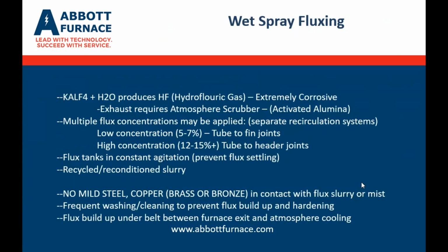As far as the HF gas, the hydrofluoric gas, it is extremely corrosive, which is why we're using an atmosphere scrubber, which is part of the issue with using the wet spray and mixing it with the flux.